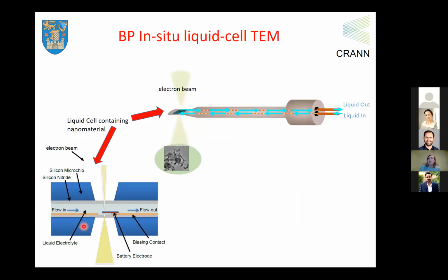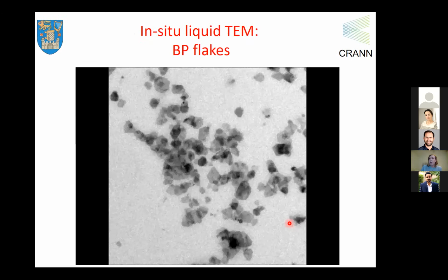And interesting to see, we did some in situ liquid cell TEM. So we basically have this holder with a silicon nitride electron transparent window, and you flow the liquid with the dispersion in here, and then you use the electron microscope to see through and see what you get. By doing that, we could actually see, let's hope this video plays, it never does, it's always misbehaving, but anyway, in some other solvents, you would see the flakes degrading almost within minutes. So you could actually see these flakes disappearing if this video was to play.